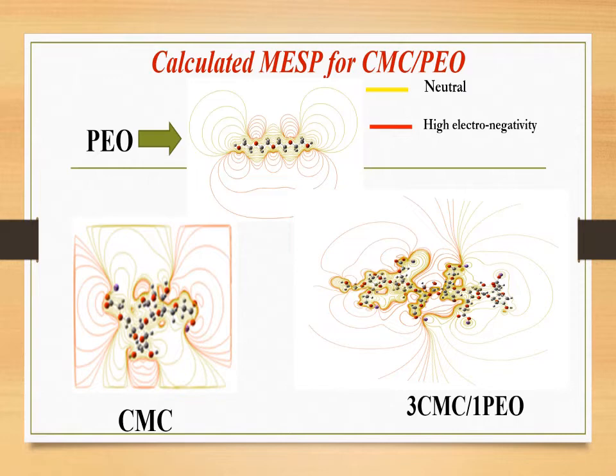As we see from the figure, for CMC the red color is present only around the edge of CMC, through the OH groups present in the terminals of CMC. Meanwhile, as a result of blending with PEO, we see that the intensity of the red color increases and is distributed around the whole molecule, which means that the molecule becomes more reactive as a result of blending.